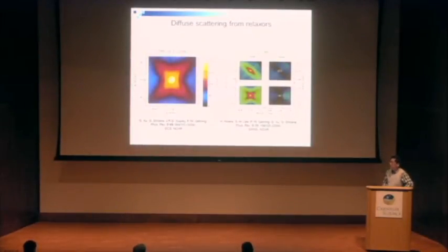Since the PNRs are atomic deviations from their perfect positions, we can use diffuse scattering to measure them by neutron or X-ray. Here is an example of measurement of PMN at 200 K. Around the 100 Bragg peak, we can see a butterfly-shaped diffuse intensity distribution extending along the 110 and 1-10 directions.